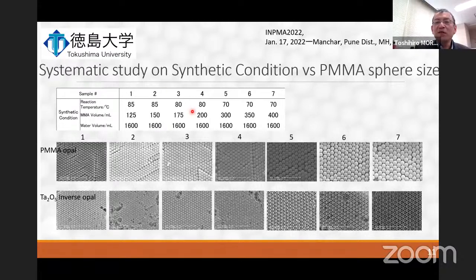So here shows the result of a systematic study of synthetic condition versus PMMA sphere size. We have 7 samples. At the polymerization of PMMA, we control the reaction temperature and MMA volume against the water. The volume of water was fixed at 1600 milliliters. After applying the colloidal crystal templating technique, we obtained high quality PMMA colloidal crystal with increasing sphere size, like this 1, 2, 3, 4, 5. You can see the radius of the spheres is increasing.